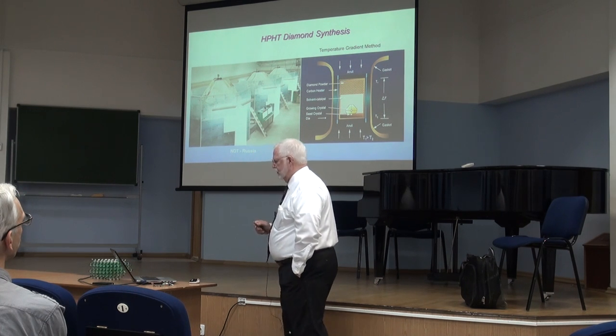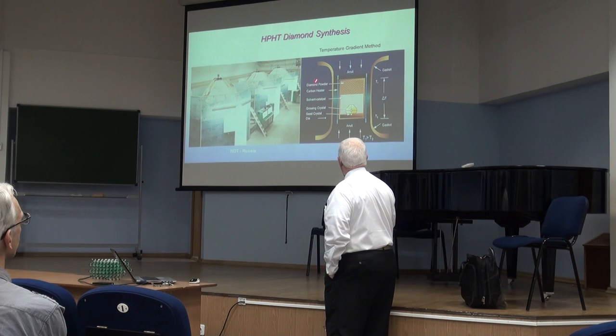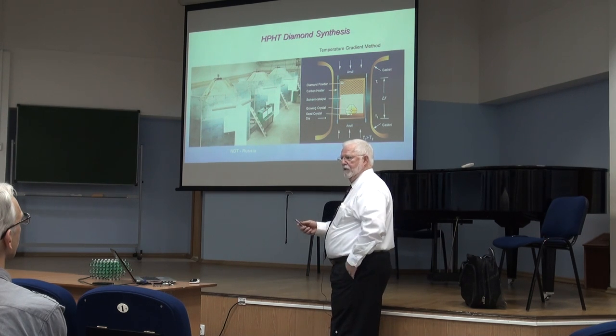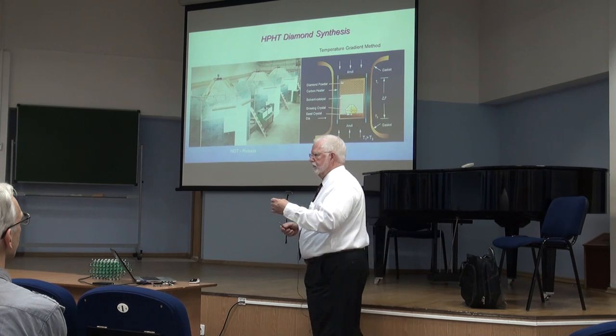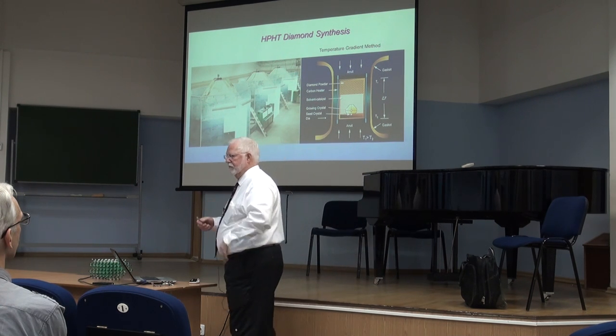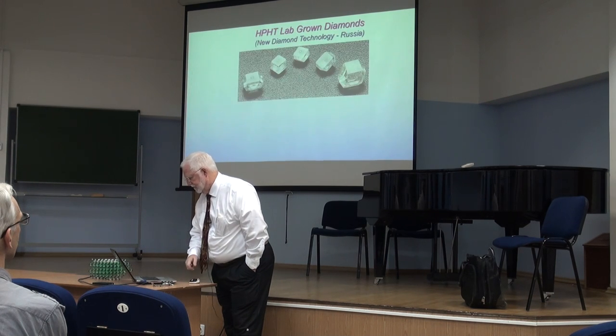The problem with this technique is achieving these pressures and using the materials to make these presses is difficult. So the largest volume that you can do right now is about the size of a teacup. So there's a limit in the size of diamonds that you can synthesize by this technique.